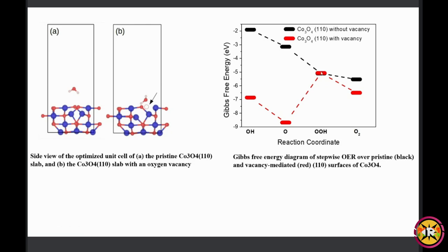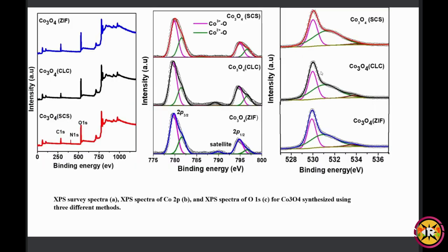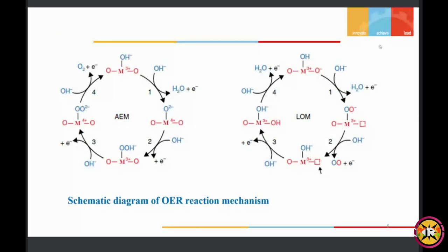So from DFT calculations also we prove if there is some oxygen vacancy, the rate of reaction will increase, as I have shown in that reaction mechanism here, LOM. If the vacancy is created here, then only the OH from electrolyte can go and sit into the vacancy, and then only the formation of O2, the forward rate of reaction, will be enhanced. So that's why oxygen vacancy in your synthesized metal oxide is the main descriptor to increase your oxygen evolution reaction.